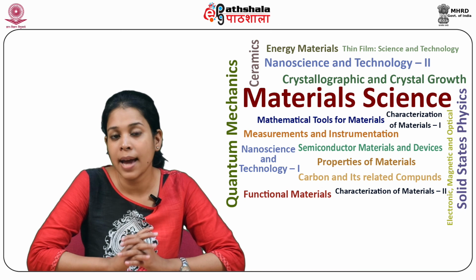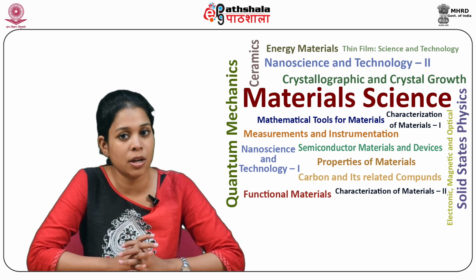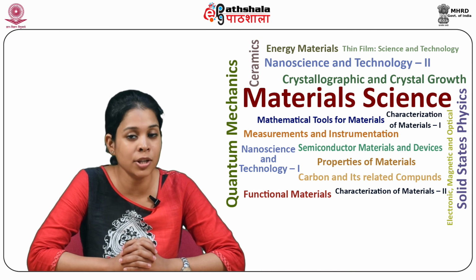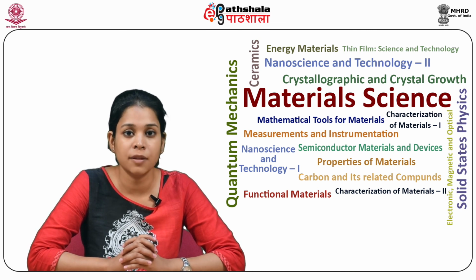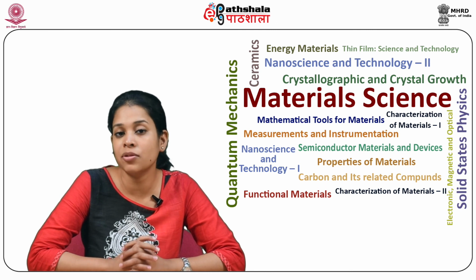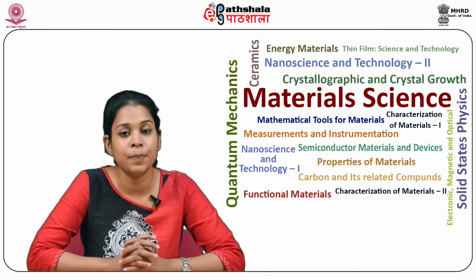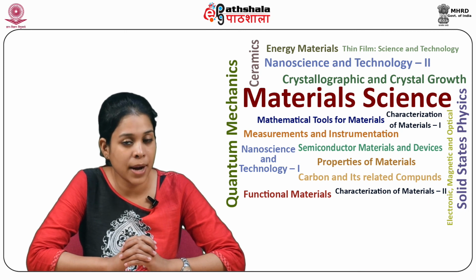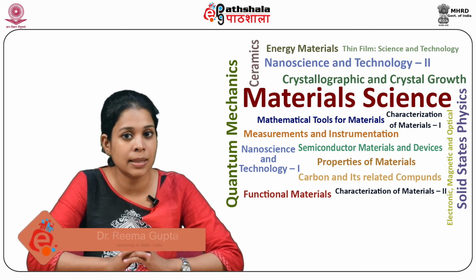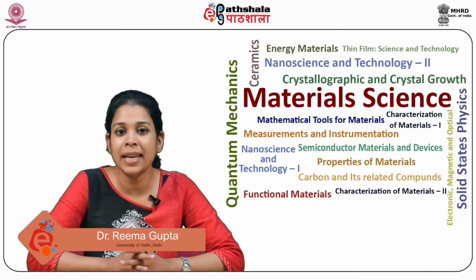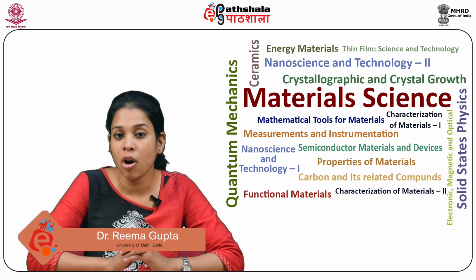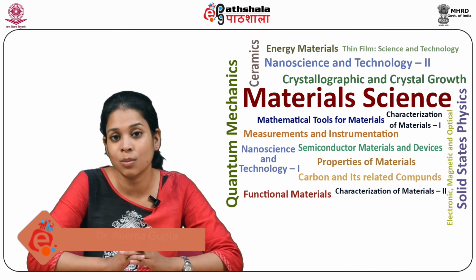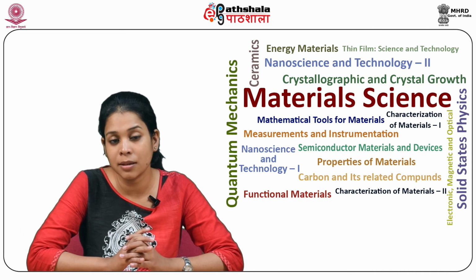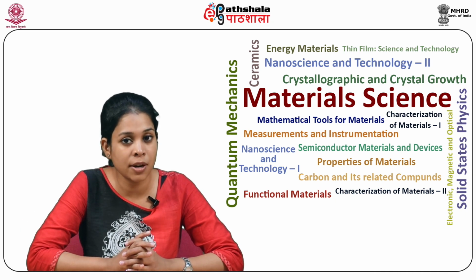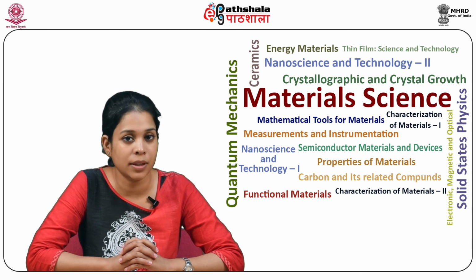So the fast ion conductors have open structures resulting in lower migration energy for defect diffusion, permitting fast transport of ions such as in beta prime and beta double prime alumina, resulting in high electrical conductivity of the order of 10 to 10 to power minus 1 per ohm per centimeter over a temperature range of 300 to 675 Kelvin. Thank you.